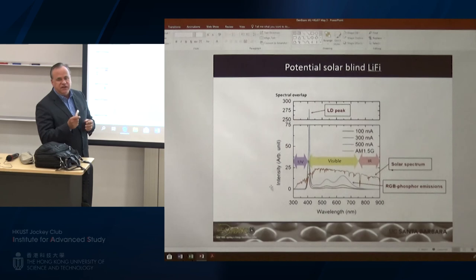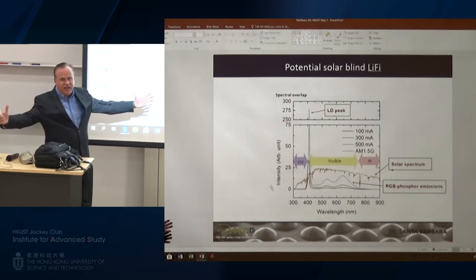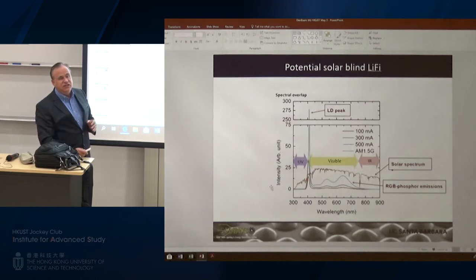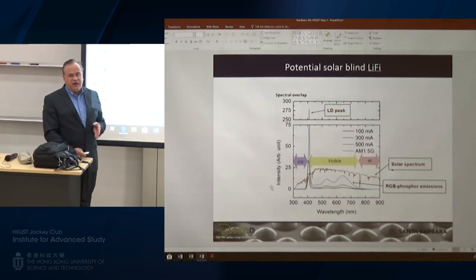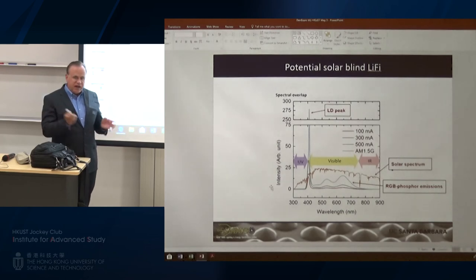Okay. So there's more surface area relative to emitting area, compared to a big LED with very little surface. And like I said, it's really bad in the red. It goes from 30% efficiency to 2 or 3%. Right. But the question, similar to the phosphor: if you have a very small emitting size, you concentrate the laser spot to a smaller size, right? But your phosphor is unconstrained. Your light is isotropically emitted from the phosphor dopants. So the spot size of the phosphor will be much bigger than your laser. How do you control that? That's the whole reason why you can't use phosphors in microdisplays, and why you need to go to direct emission or quantum dots.